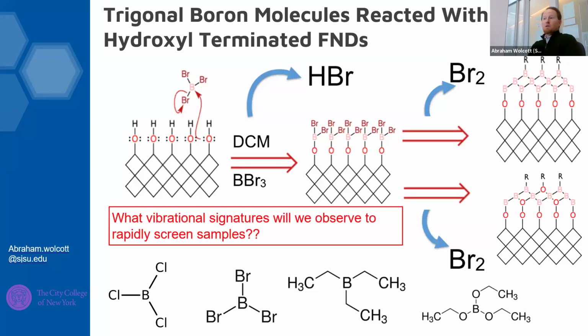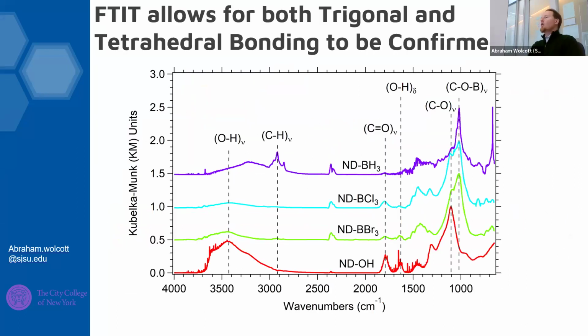What vibrational signatures can we observe to rapidly screen for these? We use air-free DRIFTS. We have a little chamber that we can bring out of the glove box. And if we do BBr3, BCl3, or BH3 chemistry, we can see this alcohol stretching mode shift, letting us know that something has happened on the diamond surface. And we show that a new carbon-oxygen-boron bond shifts by almost 75 wavenumbers to about 1025, 1015. And, you know, vibrational spectroscopy is quick. So it allows you to screen samples nicely without ever having to use the synchrotron or an XPS.